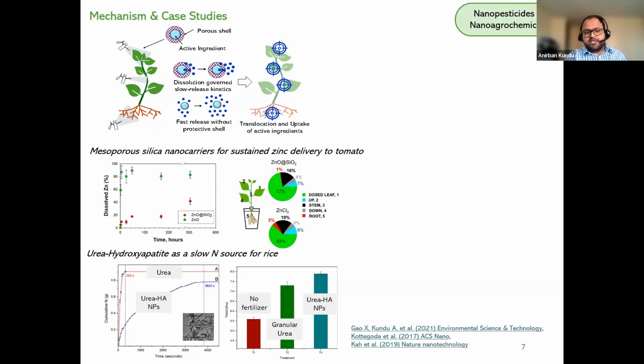So within a few hours, the amount of zinc that's released is very high. But if you look at the red, which is basically the zinc packaged in a mesoporous silica shell, the release is much sustained and much slower over time. So the plant gets the zinc over a sustained and long period of time.